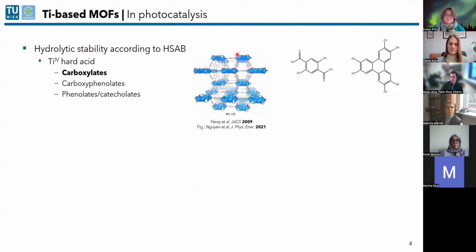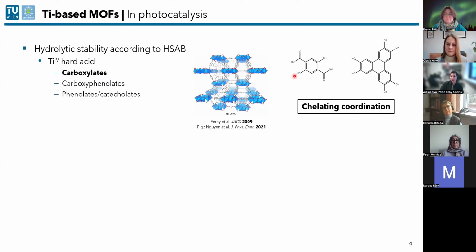But there are other coordination modes. For example, carboxyphenolates, when you look at this molecule here, dihydroxyterephthalic acid, and also purely phenolates or catecholates, like this triphenylene. The difference here, when we have these carboxyphenolates or phenolates, is that they coordinate through a chelating moiety. So usually attacking the central titanium atom, and you end up with a monometallic center because they chelate so strongly. And this has some impact on the absorption properties, but also on the photocatalytic properties. So maybe we will get to that later.